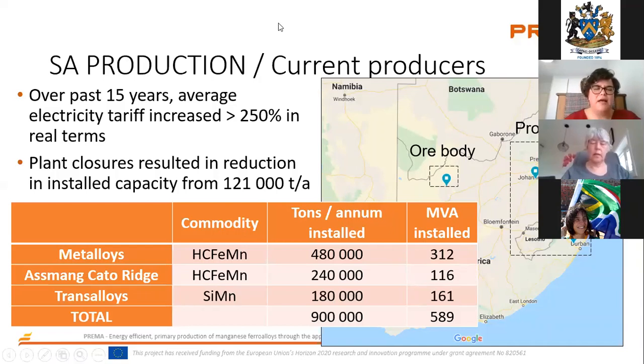Over the past 15 years, the average electricity tariff in South Africa increased by 250% in real terms. And that resulted in plant closures, with a significant reduction in installed capacity, plants being mothballed. So the only ones in operation are Metalloys, Assmang Cato Ridge, and TransAlloys. Metalloys and Assmang produce high carbon ferromanganese. They don't necessarily run at full capacity at this stage, but at 50% or less, and they also produce medium carbon ferromanganese using converter technology. TransAlloys, as I mentioned, produce silicomanganese, and they run at full capacity.